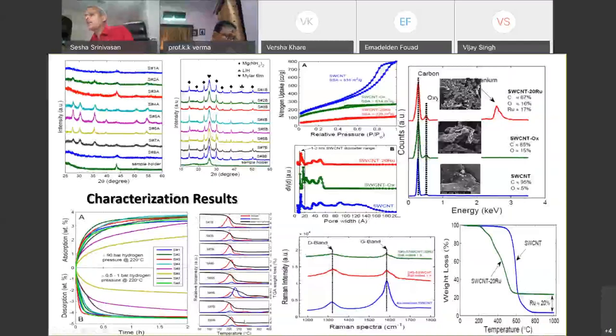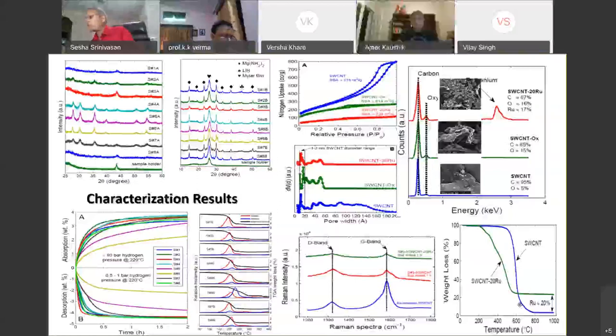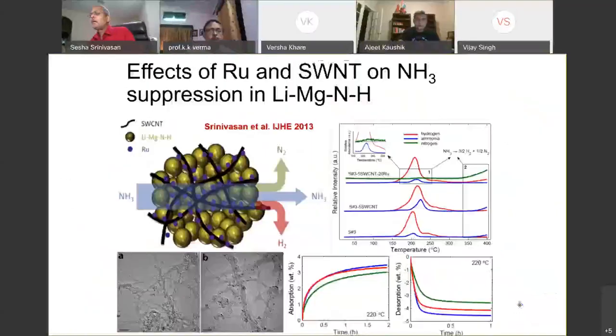We wanted to see that by mixing single wall carbon nanotubes with a 20% ruthenium catalyst, we could reduce or suppress the ammonia so that you can increase your hydrogen desorption characteristics. So this is the way one has to look at how to optimize by using material synthesis and then characterize it so that you can know where the optimum is for your applications. So this is the process we were closely looking at, having ruthenium as well as single wall carbon nanotubes. Look for the hydrogen peak, which is increasing, the red, and the ammonia is decreasing, and the green peak is growing, that's called nitrogen. So ammonia is cracking down into nitrogen and hydrogen so that you can use more hydrogen, less ammonia. That's good for your fuel cell vehicle applications.